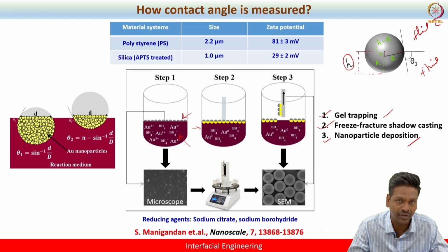This chloroauric acid will nicely sit on the surface of the polystyrene, whereas the sodium borohydride will help reduce the chloroauric acid, so that the nanoparticle nucleates on the surface itself and grows over the surface. So this is how you create a deposition of nanoparticles on the surface exposed to the water side. Remember, there is no deposition on the air side, because there is no wet chemical reaction going on the air side.